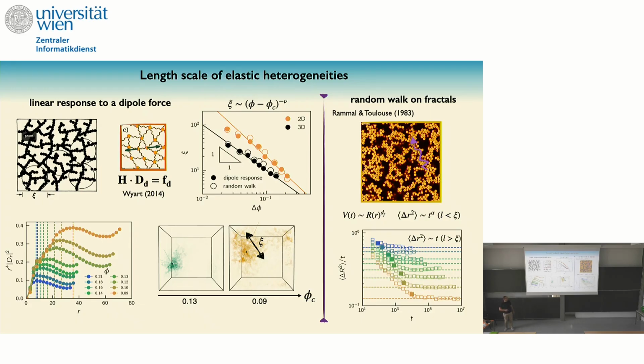And if you do that and extract this length scale, here I'm not telling anything about the elasticity, just about the structure. I just need to know the position. I know the position and I extract this length scale that corresponds to the crossover from the subdiffusive toward the diffusive regime. This is the open symbol. See, it corresponds very well with this mechanical length scale that we extract.